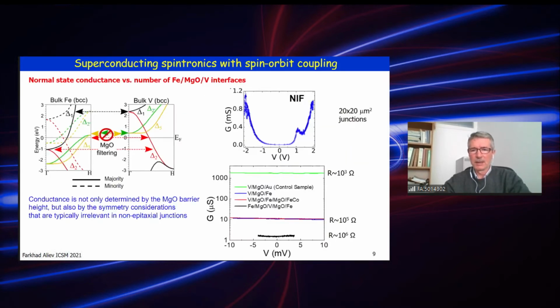If we have a control sample, for example vanadium, MgO, gold, it's a highly conductive tunnel junction. While if we just introduce the interface between vanadium and iron, the conductance drops two orders of magnitude. If we introduce two interfaces, it will be further dropped. So this is vanadium sandwiched between two iron layers.